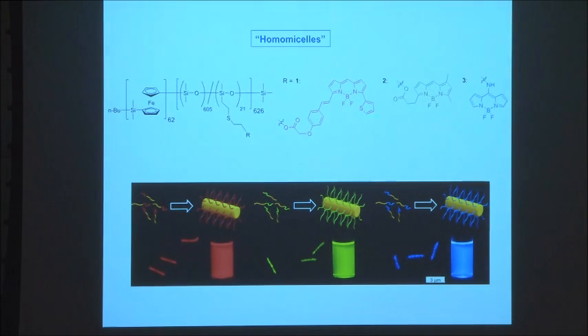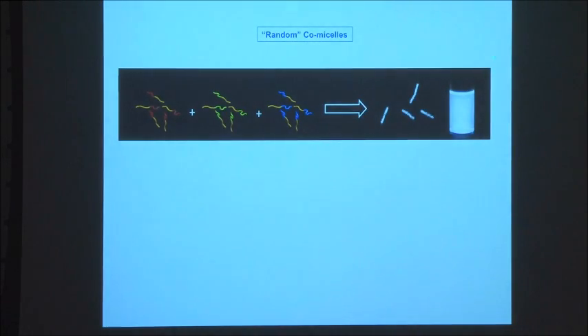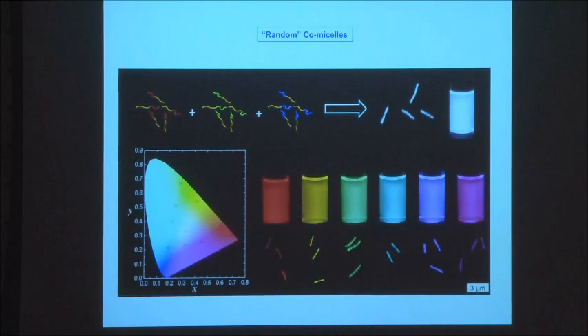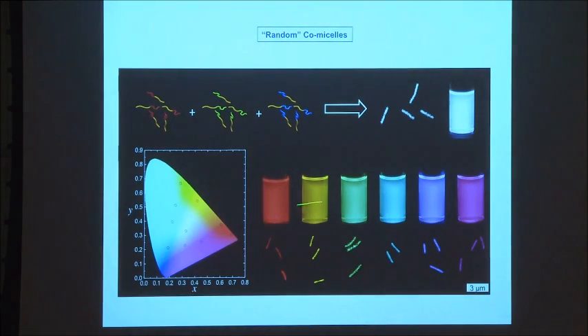But very interestingly, what you can also do is make analogues of random copolymers. So you can take mixtures of the material with a red dye, the material with the blue dye, the material with the green dye, in any ratio you want, and then control the structure of the resulting micelle. So you can even make white micelles by taking the right ratio of these block copolymers. You can go all over the chromaticity diagram and make any color you want within this structure just by varying the amounts of these that you use. So these are random co-micelles, if you like, that you generate here that generate the different colors according to the chromaticity diagram.